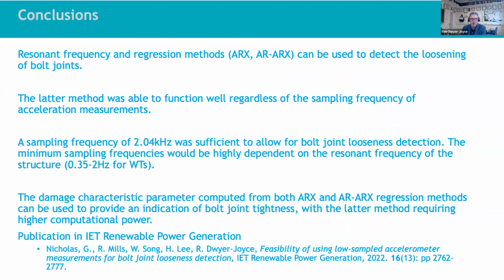So in conclusion, Gary tried resonant frequency methods and regression methods to detect the loosening of the bolt joints. The regression methods were able to function well regardless of the sampling frequency of the accelerometer, so we were able to do it at 50 hertz and 2 kilohertz. The resonant frequency methods could detect loosening of bolts, but not which bolt was loose. A sampling frequency of 2 kilohertz was also sufficient to detect bolt joint loosening.